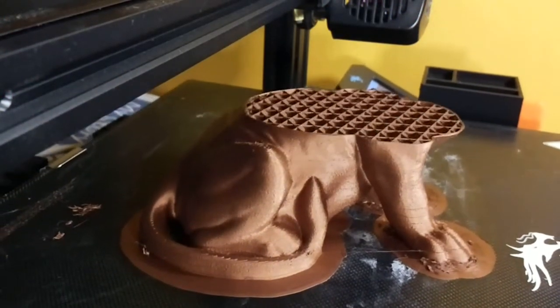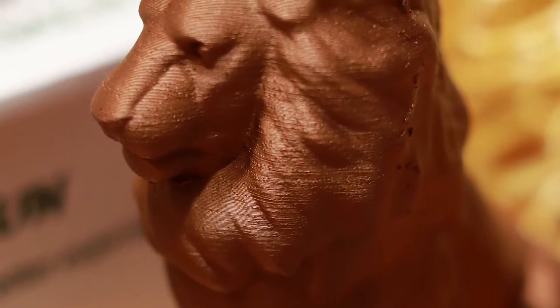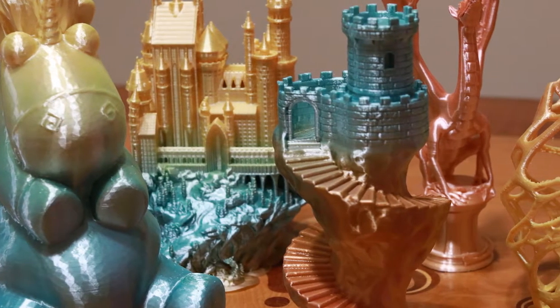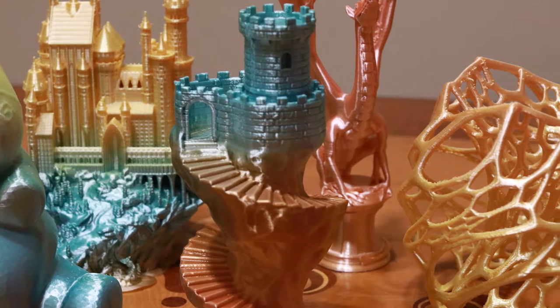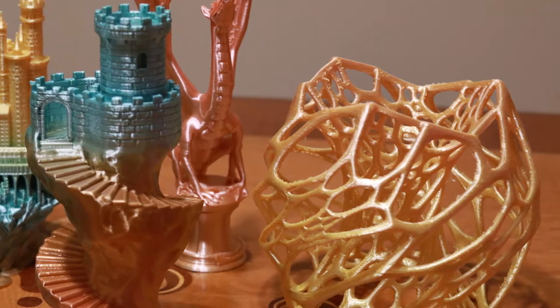The copper filament is the only filament that I found more difficult to work with, as it tended to form clumps if the nozzle temperature is too low. Make sure that you increase your temperature for this one on larger prints. My personal favourite is the rainbow filament, which transitions between a range of metallic colours. As with all colour changing filament, the exact colour transitions will vary from model to model, so make sure you choose a model size and infill percentage that gives the filament a chance to cycle through the different colours at your preferred rate.